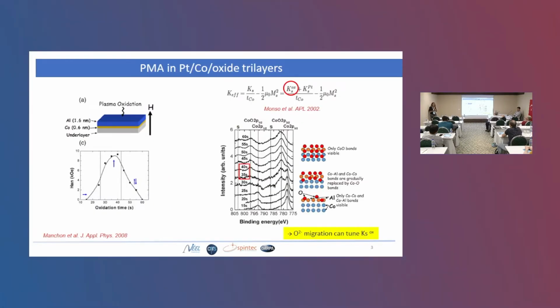So I go back to something that has been introduced this morning already: what we know about PMA, perpendicular magnetic anisotropy, in this kind of trilayers, platinum cobalt covered by an oxide. This was the work of the Spintec group 10 years ago. They showed that there is, of course, a strong contribution to the anisotropy coming from the platinum cobalt interface that we know, but there is also a contribution coming from the top interface, the cobalt oxide interface. And this contribution depends on the state of oxidation of the cobalt interface.